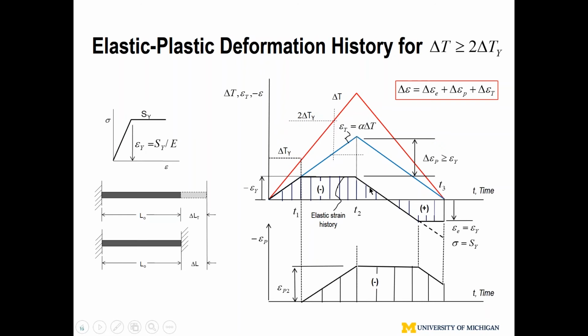Because this is under fully restrained, under compression, so this is negative. I put a negative on top, so I can use PowerPoint easily to make this sketch. That means this area plus this area equals total thermal strain available, which is the blue line. Once I exceed delta Ty, I'm going to have a permanent effect. So in that case, on cooling, when I reach peak temperature, the thermal strain available is here because I ended up with elastic strains here. So I move this line in parallel, so I can continue to examine the cooling effect.